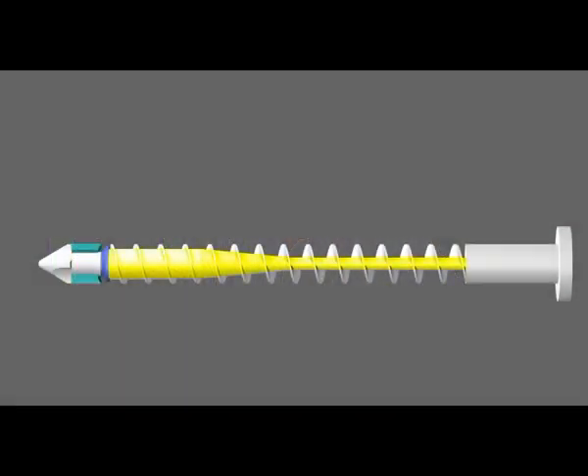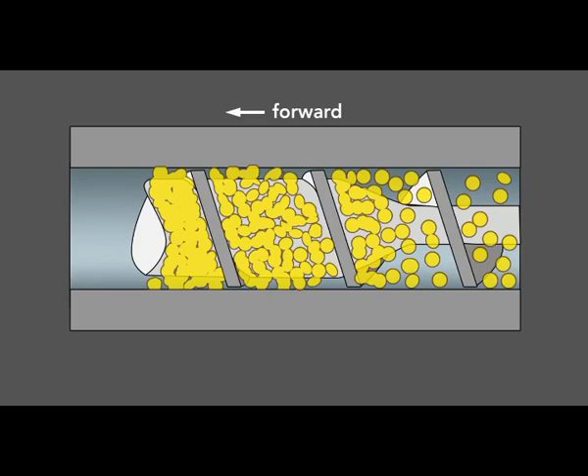And third, the screw action itself heats the plastic throughout. The shaft's diameter increases along the screw, so that the distance between the wall and shaft decreases. The flights then squeeze out air as they move the plastic forward, and they shear the pellets and press them against the barrel's wall. This shearing creates friction and so heats the plastic throughout.